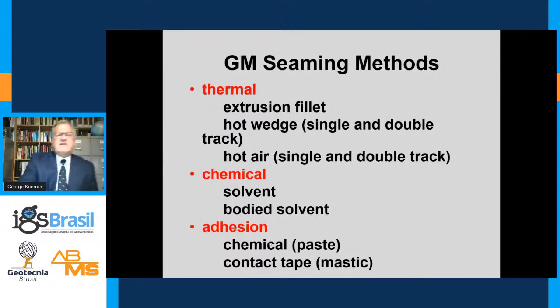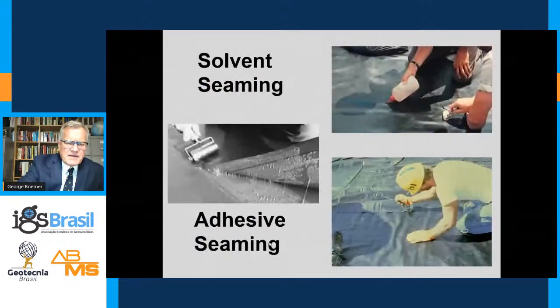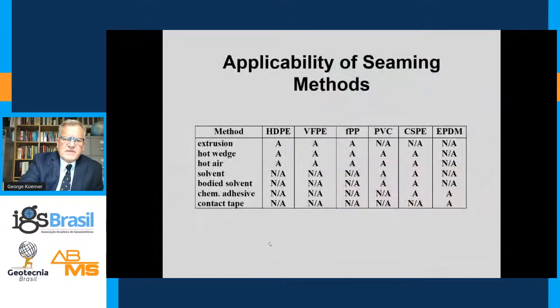As far as the seaming methods, it's very dependent on the type of materials which are used. The olefin plastics, which we described, are seamed thermally, either through extrusion or fusion welding. Fusion can be done off of a wedge or hot air. Chemical seaming with solvents or bodied solvents are done with PVC and chlorosulfonated polyethylene. Adhesives are typically used with EPDM. Solvent seaming and adhesive seaming we don't see much of these days. Even PVC can be thermally seamed, although this is available to you, and we see it often in the roofing business, but not so often in the field business except with EPDM.